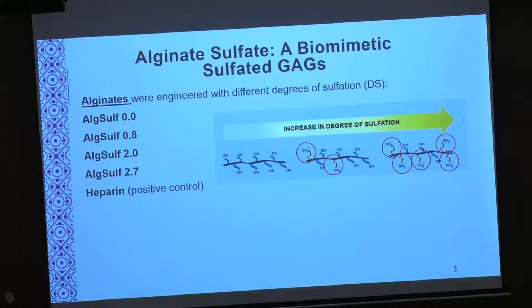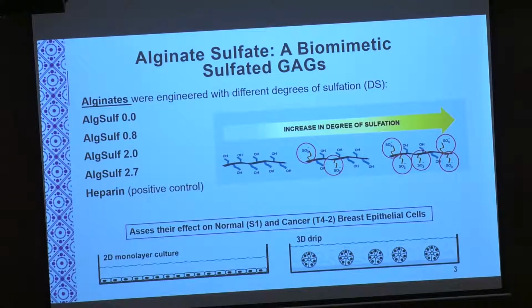We added sulfate groups to them, and we will be referring to the sulfation patterns as degrees of sulfation that will be ranging between 0, 0.8, 2.0, and 2.7. And we're going to use a positive control, which is heparin, a naturally occurring glycosaminoglycan with a degree of sulfation of 3, so it's maximally sulfated. And we're going to assess their effects on two cell lines, the normal S1 cell line and the T4 cancer cells, using two models: the 2D monolayer culture where cells are grown in plastic, or the 3D model where cells are grown in hydrogels.